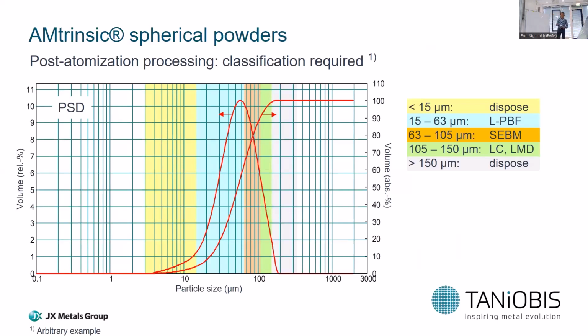The first thing that we do is, because we usually have quite a broad particle size distribution, from very small to very coarse, we remove the very coarse fraction above 150 micrometers simply by sieving. So it's scrap of very big particles. The next step is we dispose of the very small fraction below 10 to 15 microns, because the small particles are detrimental to the powder flow.